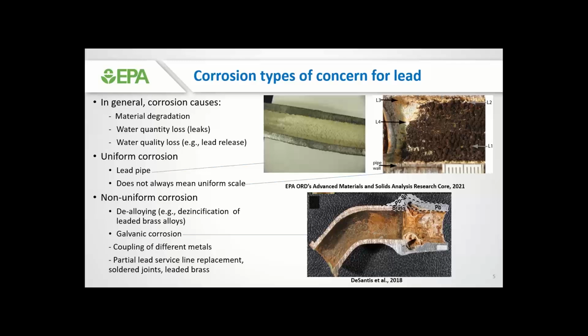We have, of course, other types of corrosion that are important for lead that are localized or else not uniform. One of those would be de-alloying. This would affect leaded brass alloys. For example, dezincification is the preferential dissolution of zinc from the brass, which may impact the other metals in the alloy as well, including lead.